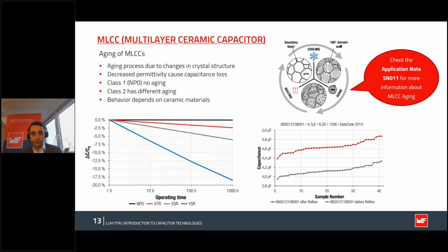In order to show that to you a little bit further, we have the measurement on the right here. You can see we tested some samples before soldering in gray, and after the soldering in red. And you can see they've pretty much been restored after the soldering in. So the capacitance drop of close to 0.5 microfarad basically has been negated by the soldering in.